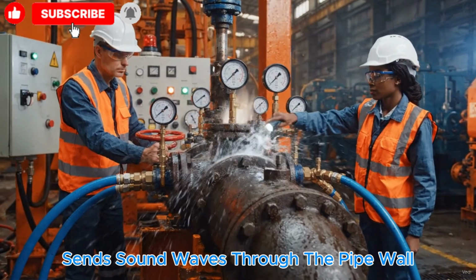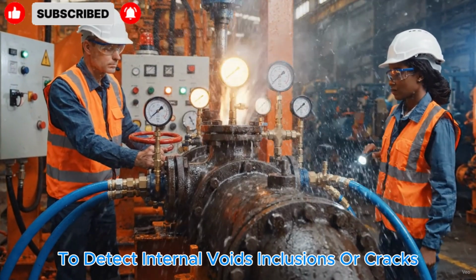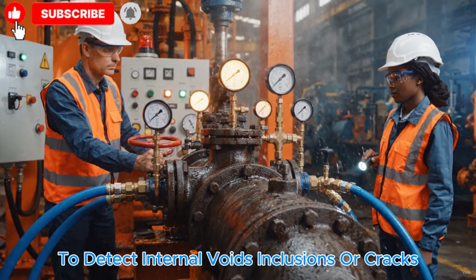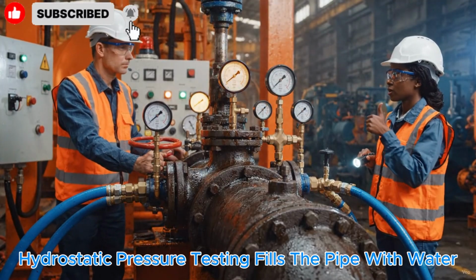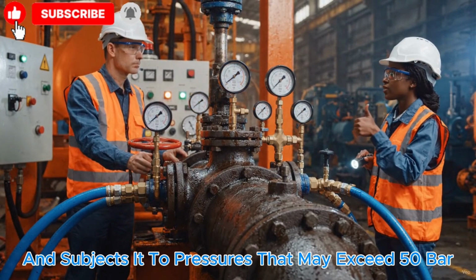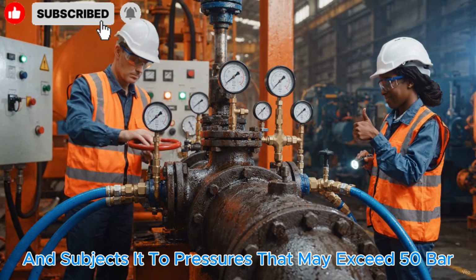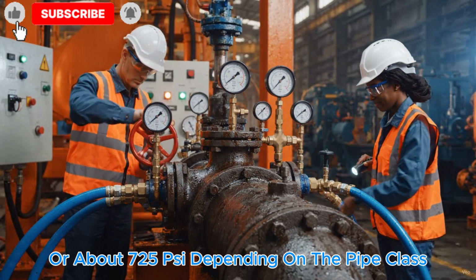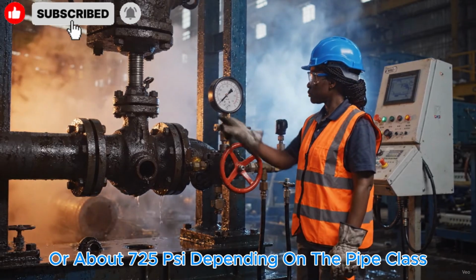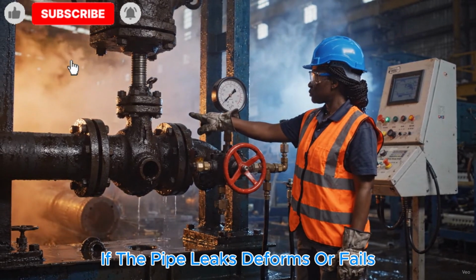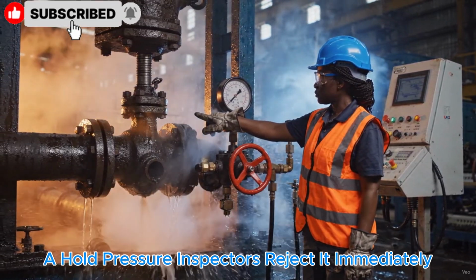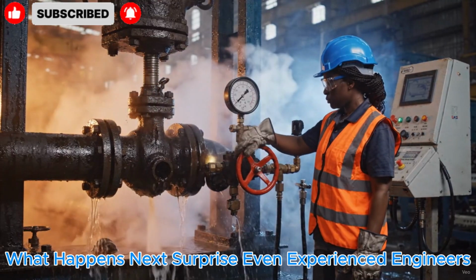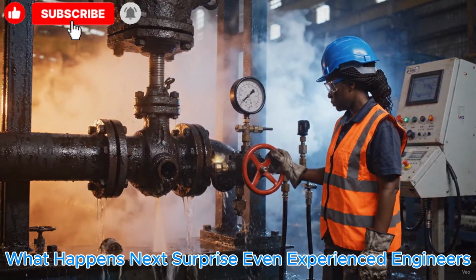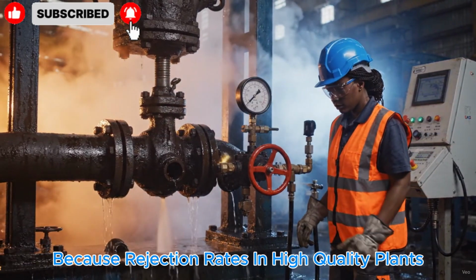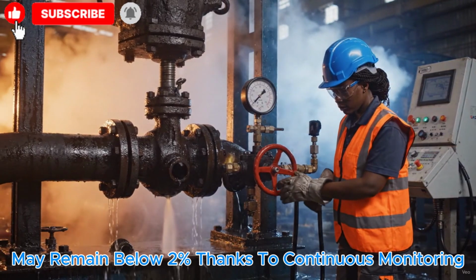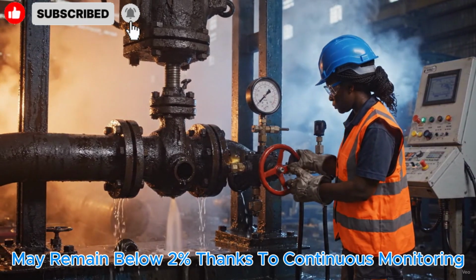Ultrasonic testing sends sound waves through the pipe wall to detect internal voids, inclusions, or cracks. Hydrostatic pressure testing fills the pipe with water and subjects it to pressures that may exceed 50 bar, or about 725 psi, depending on the pipe class. If the pipe leaks, deforms, or fails to hold pressure, inspectors reject it immediately. What happens next surprised even experienced engineers, because rejection rates in high-quality plants may remain below 2% thanks to continuous